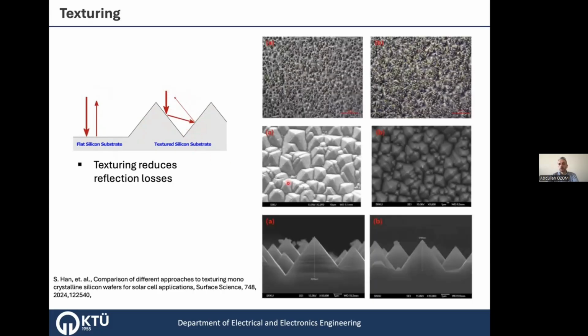Here are some real images of the silicon surface. These on the left are microscope images, optical microscope, I guess, and these are SEM images and the cross-section images. Actually, both are similar, but the etching process is different. This one is the sodium hydroxide etch process, I guess, and this one is the potassium hydroxide etch. You see that the formations are similar. You have random pyramids on the surface, very clear, nice pyramids that will decrease the reflection on the front surface.